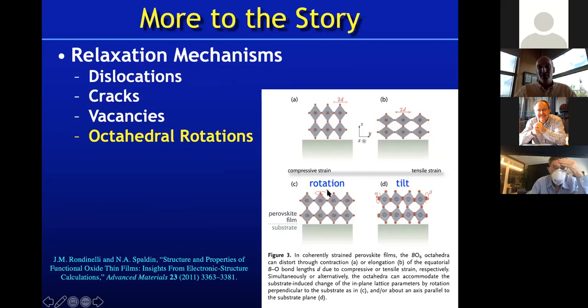Okay, sorry. So in the case of compressive strain, another way to take that up is you can simply rotate the octahedron, and that brings everything smaller in plane. Or we could do what's called tilting, which is a rotation along an axis that's in the plane. So these alpha and beta angles here are in the plane of the substrate. And if we tilt by one of those axes, then it gets longer in the plane, which would be a way to accommodate the different lattice constant of the substrate.